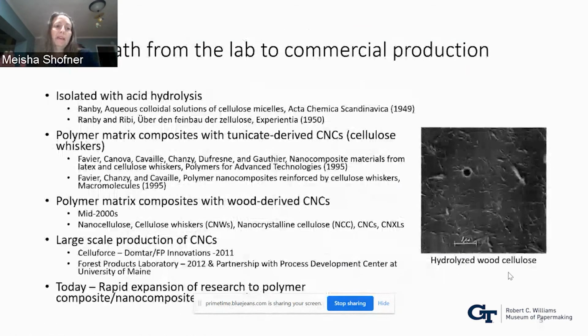So if we think about how we got to where we are with these materials, they have been known for a while. As people were trying to understand the structure of cellulose fiber, one thing they did was subject it to acid treatment, or an acid hydrolysis. Through that process, they ended up producing these nanocrystals, not that they were necessarily trying to use them as a finished material, but rather as a way of understanding structure. And you can see an image of those fibers as produced from these papers around 1950.